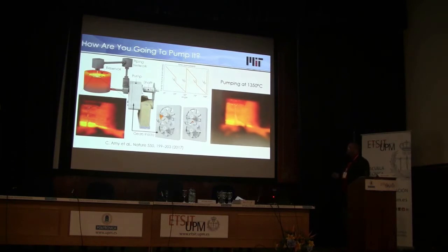So this is a project we did a few years ago. First thing we pumped was liquid tin. So this is the way the system was arranged. It's basically a graphite crucible with tin. Tin and carbon do not form any chemical compounds, so they work very well together in the sense that the tin is not even wetting for graphite. So you could just make an all graphite system.